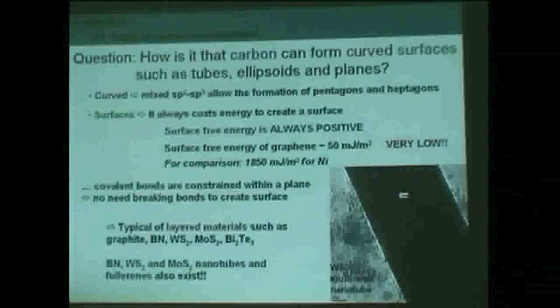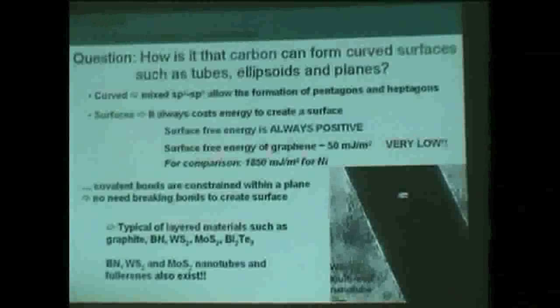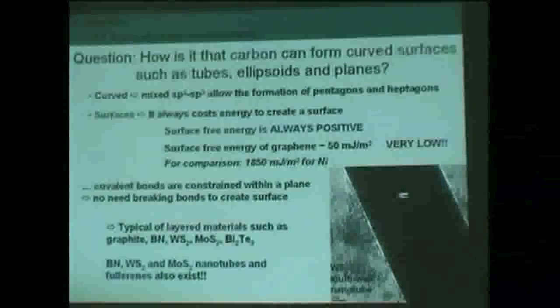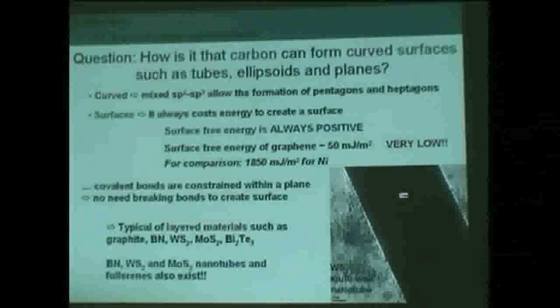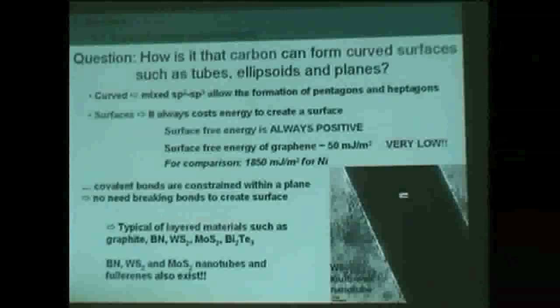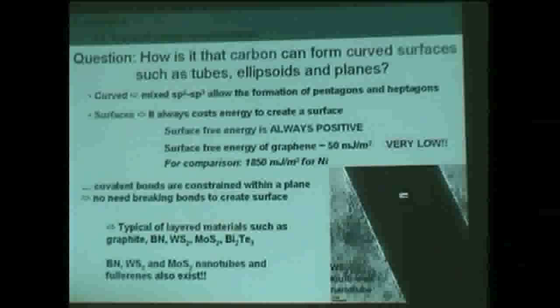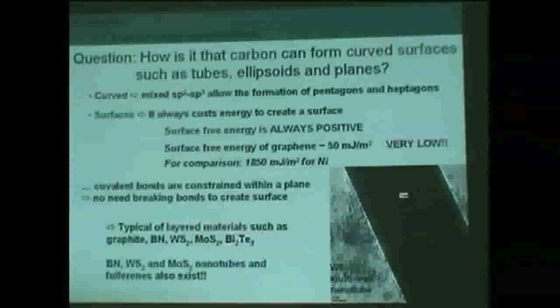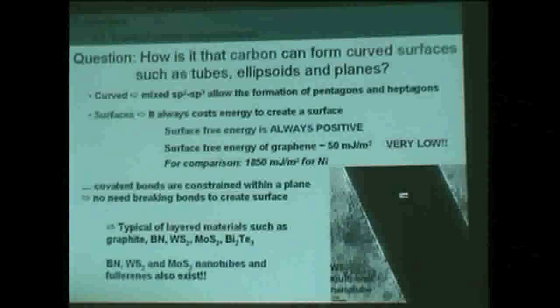So there are other types of materials that have a very low surface free energy, and those materials, like graphite, like to create layers stacked together in a three-dimensional material. They are not just graphite; there are many other types of layered materials. Examples are BN, disulfide of tungsten, disulfide of molybdenum, and this kind of tellurium. They make layered materials because they have very low surface energy, like graphite and graphene.